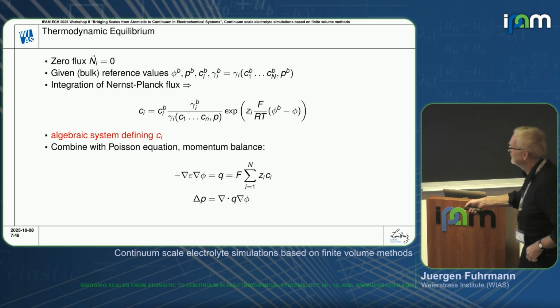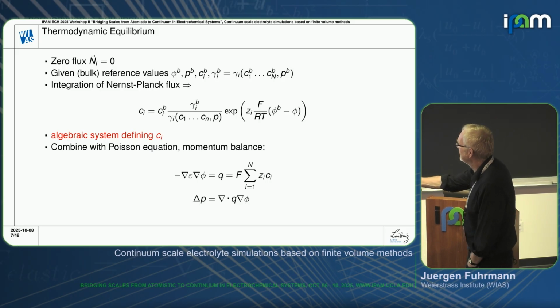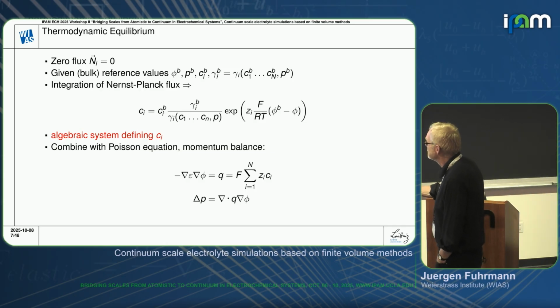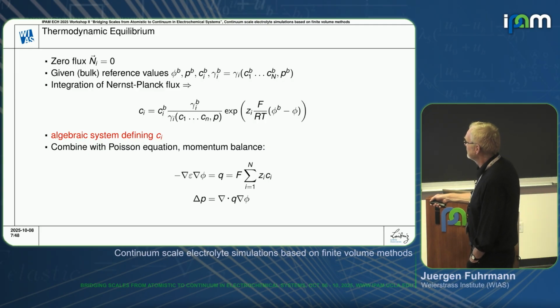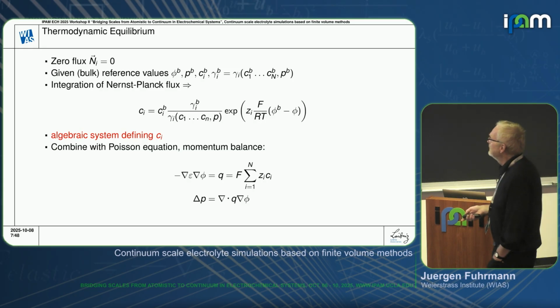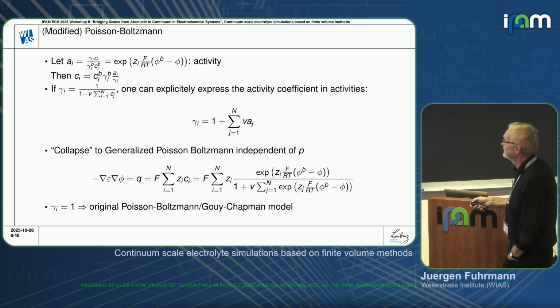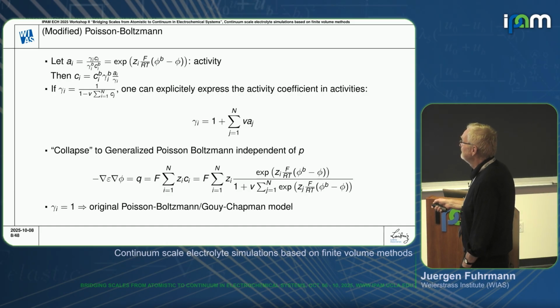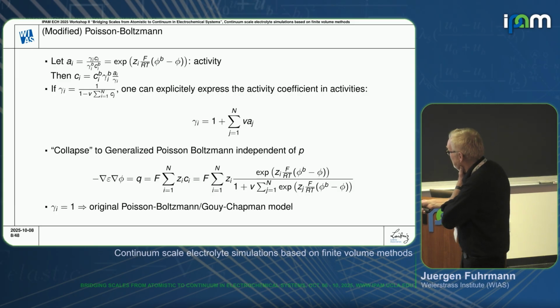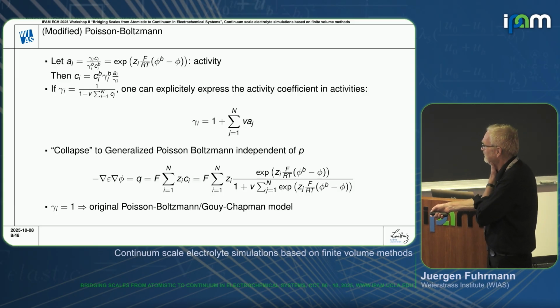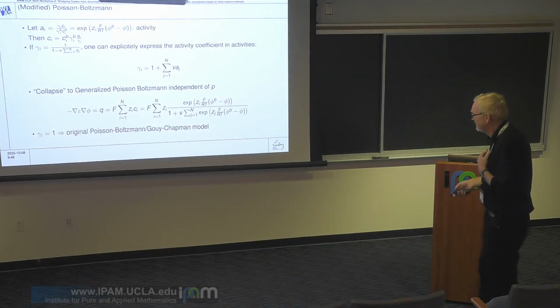So in this case, where we write it in this general form, we have these two PDEs and the corresponding algebraic equations which describe the concentrations, and all this needs to be solved together in a consistent way. We can also simplify the model, assuming that all molar volumes are the same, and express the activity coefficients in activities, and then everything collapses to the well-known generalized Poisson-Boltzmann system, where we have the activity of the species on the top, and then 1 plus molar volume times the sum of the activities of the species in the denominator. And if gamma would be 1, then we would go back to the original Poisson-Boltzmann or Gouy-Chapman model.